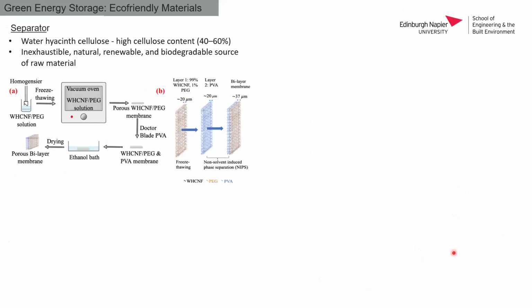Okay. Further to this, as I mentioned previously, the separator is one of the most important parameters in electrochemical devices. There are different types of separator used for green energy applications or clean energy solutions. You need a material fabricated using more cellulose-based material. So what we did is use plant-based material, water hyacinth, where the cellulose content is very high. One of my PhD students converted that into a bilayer separator membrane.